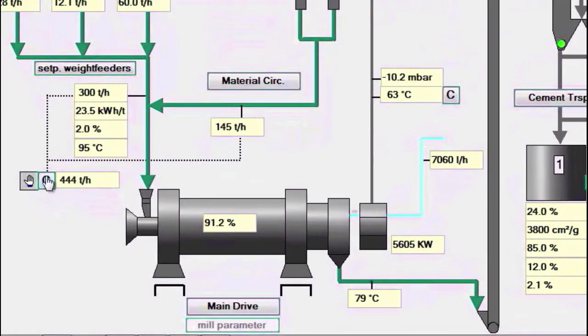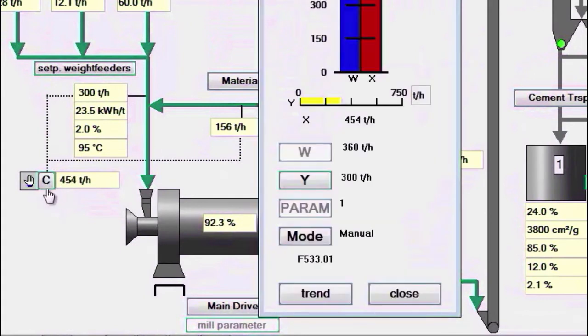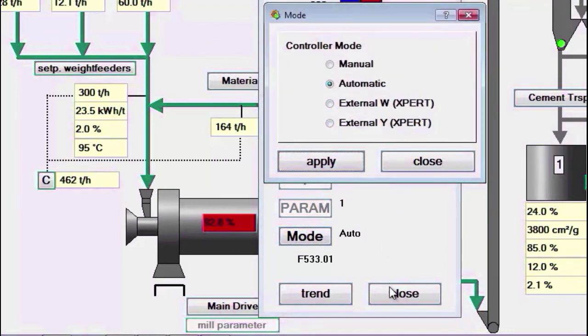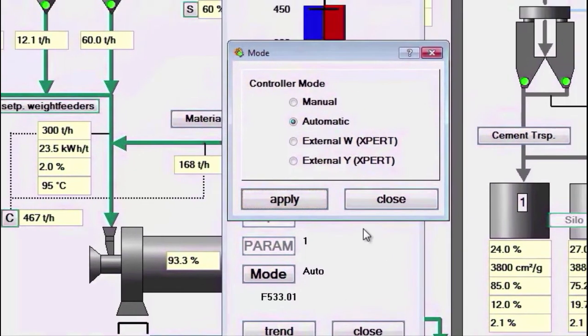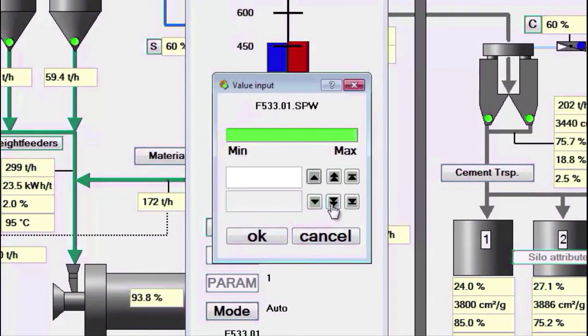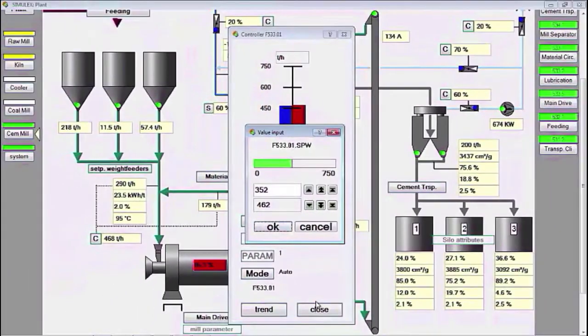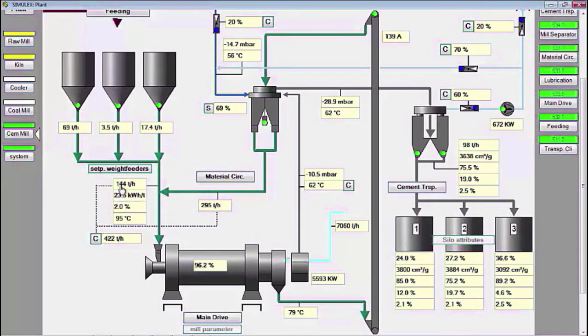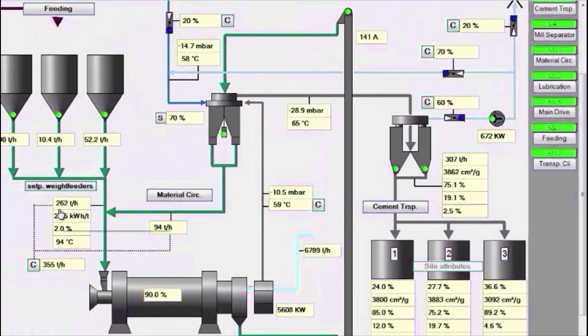This material in the mill is full, we control it by changing the set point total sum to automatic, and setting feeding to 350 tons per hour, so that the material in the mill is not full. At the start of the cement production process at the cement mill, the first time we feed using a manual setting, for example, a production capacity of 200 tons per hour, we set the manual setting to fresh feed, while the automatic setting is set to the total of tailings material and fresh feed.